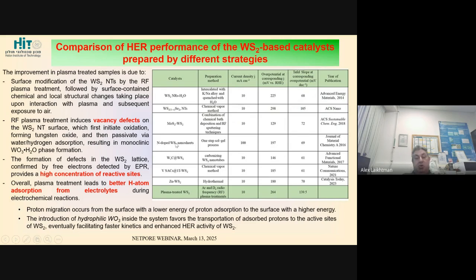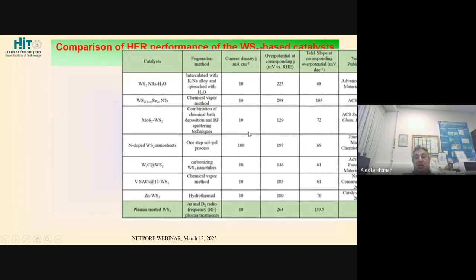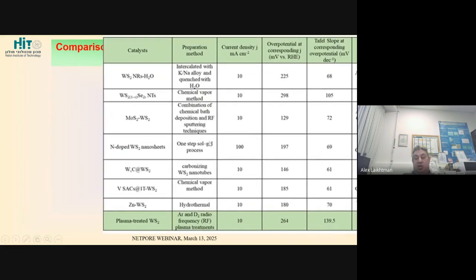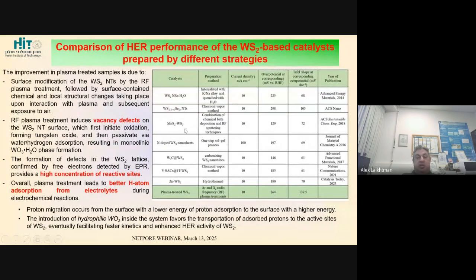Most of them are based on WS2 or WS with other compounds. And then we observed that our results are still not the best, because as I have just told you, we obtained 264 overpotential, while in other materials it was slightly lower, though their preparation and process was much more complicated than in our case. So then we considered how we can further improve the results.